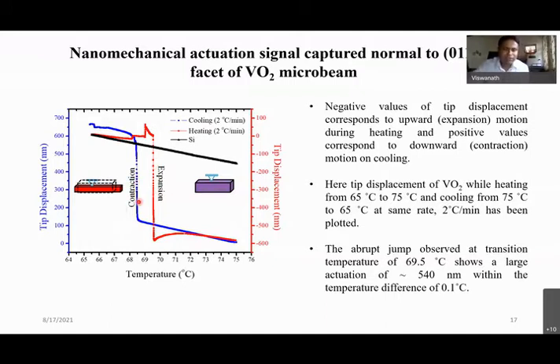Of course, there are some frictional forces involved during the phase transformation. So during heating, the phase transformation temperature is 68 degrees Celsius. But during cooling, for thin film, the temperature could be at least 5 to 10 degrees Celsius lower. In single crystal, the hysteresis is relatively small. The temperature difference between heating and cooling can be as low as 2 degrees Celsius.